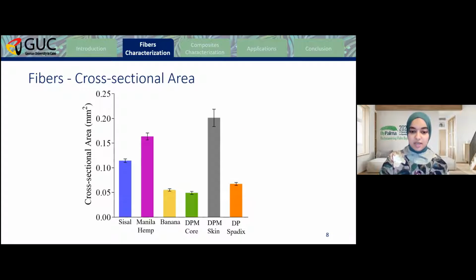As for the cross-sectional area analysis, we found that the smallest cross-sectional area was for the date palm midrib core fibers and the banana fibers, followed by the date palm Spadix stem fibers. We also found that the date palm midrib skin fibers had the highest area values, and this could be due to the large amount of impurities found on the surface of the fibers, which may make it somehow difficult for the penetration of the caustic soda, and we are going to further investigate this point.